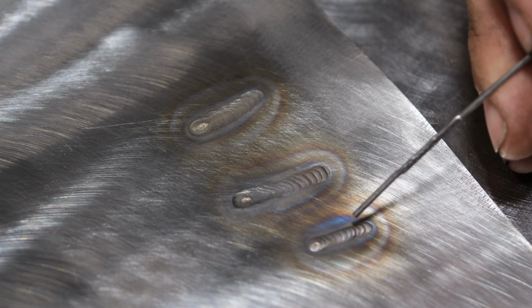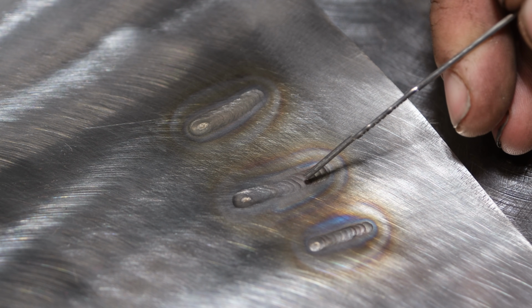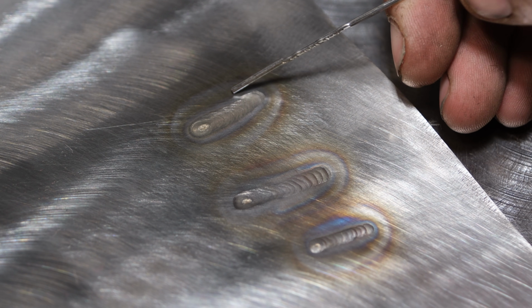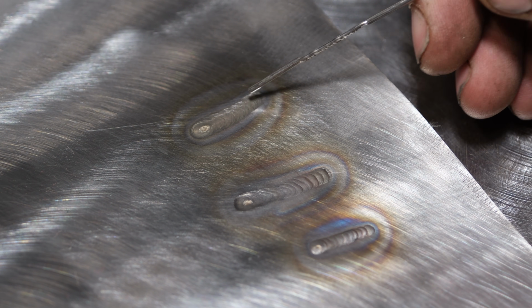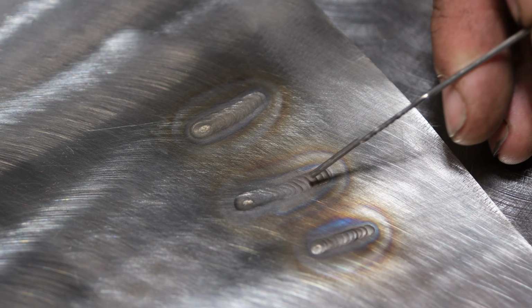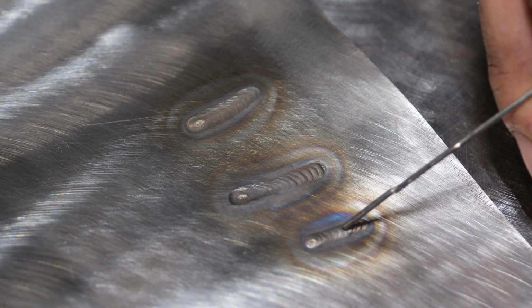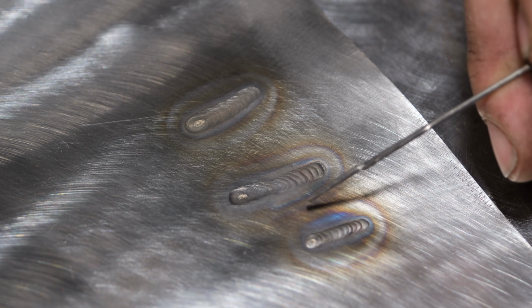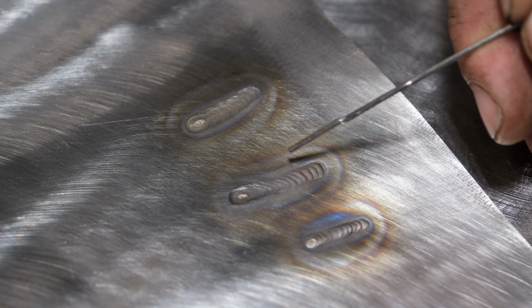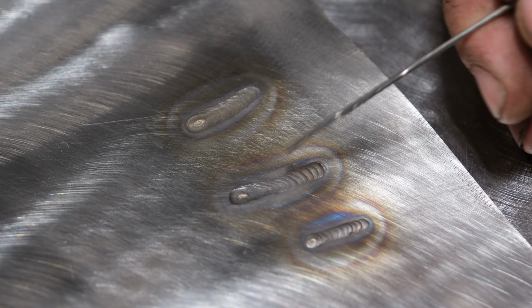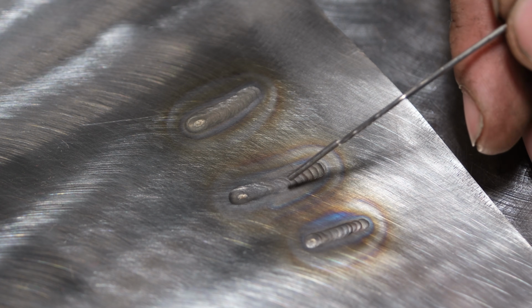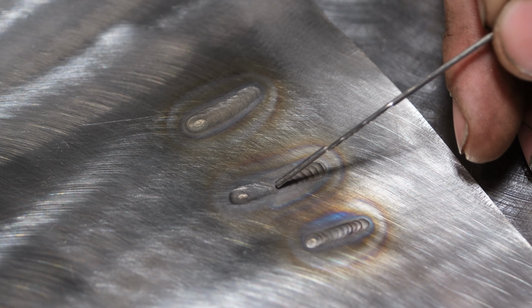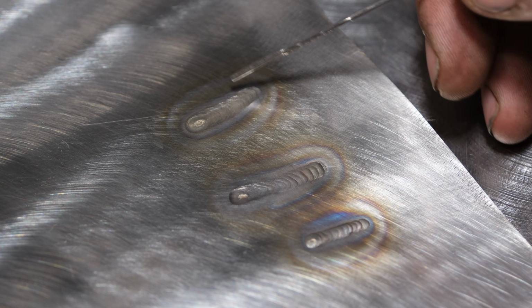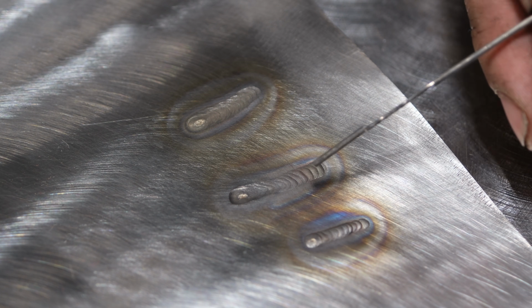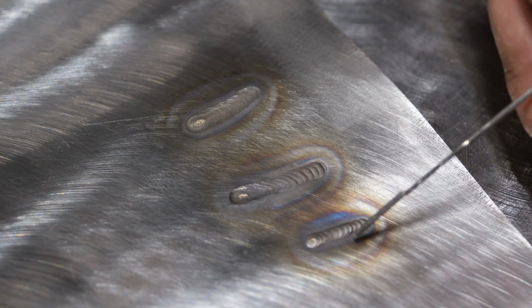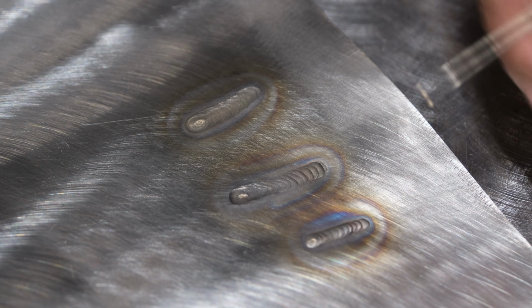So you can tell looking at this, basically all of that color just comes right off. You don't really see any dull grays in here. This, due to how much it's sunk in, looks a little bit darker, but it's basically, from my view, as shiny as these. This is the most shiny out of them. But that has a lot to do with the fact that it's sitting above the plate and it's reflecting light differently. These two are both sunk in. But anyways, nothing here with the color is defective. The weld is not weaker because of it. This is not titanium. With titanium, all that color you saw in this one and this one would mean the base material is junk. But we are all acceptable on this side with this.